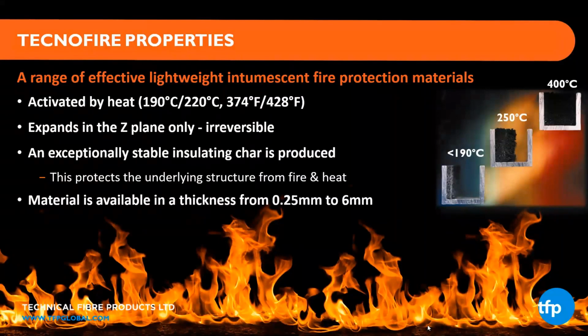So the Tecnofire expands, as Neil had pointed out. If you look at the graphic on the right, we're going to be activated. That expansion will begin around 190 C, 374 degrees Fahrenheit, but not much is going to happen at that level. Once we see a larger amount of heat, a higher flux or a higher amount of heat into the system, you will see that expansion. If you can see, the middle graphic is at 250 C and then up to 400 C. Realistically, the full char layer is in that 400 C range.